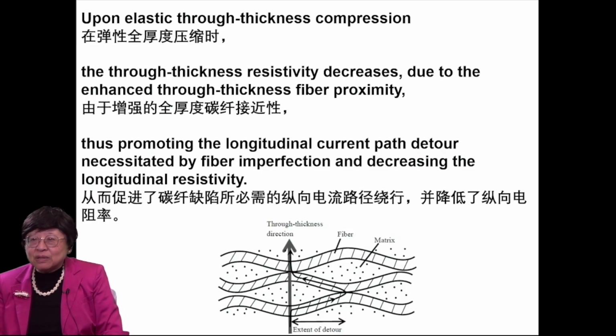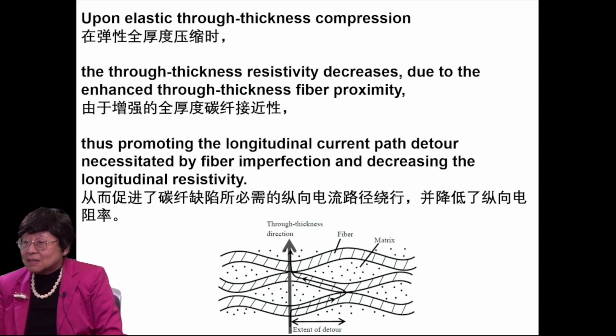Now, upon elastic through-thickness compression, as I said, the through-thickness resistivity decreases, and that's due to enhanced through-thickness fiber proximity. But this effect also promotes the longitudinal, the horizontal direction, current path detour that's necessitated by fiber imperfection, which is always present. And that would cause the longitudinal resistivity to decrease. So instead of measuring the through-thickness resistivity decrease, one can measure the longitudinal resistance decrease. And both work to allow us to monitor the effect of through-thickness compression.